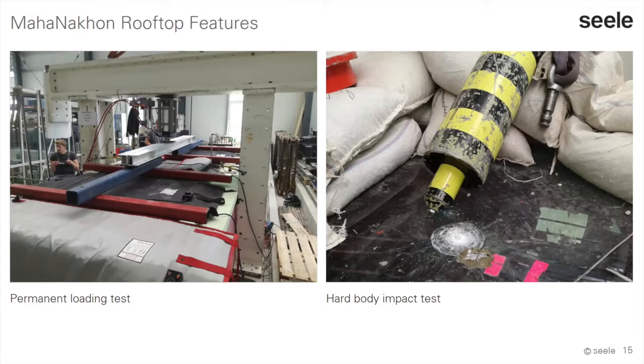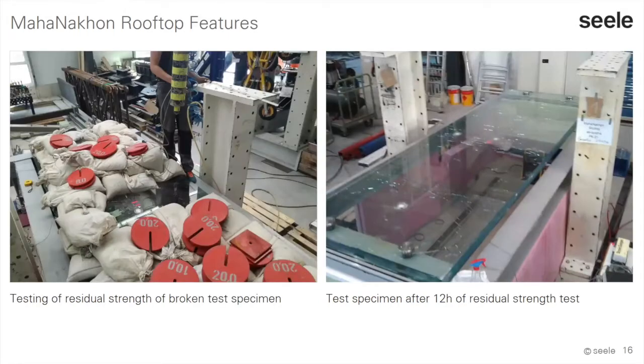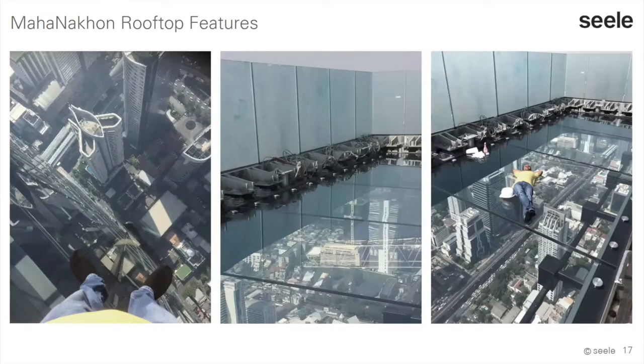So we did a permanent loading test. We did the hard body impact testing after the glass broke. With the hard body impact testing, we did a residual strength of the broken test specimen. We did, then on the right-hand side, you see the test specimen after 12 hours of residual strength test. And then this is after all of that was installed. Somebody standing in the glass and looking down 300 meters without any horizontal support below the joints between the glasses.